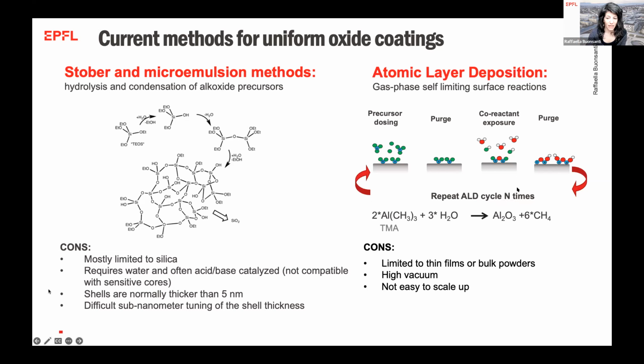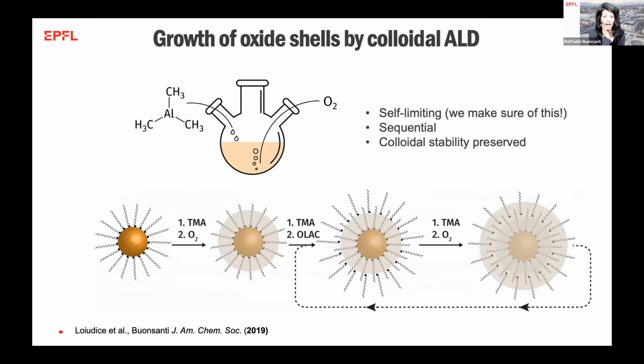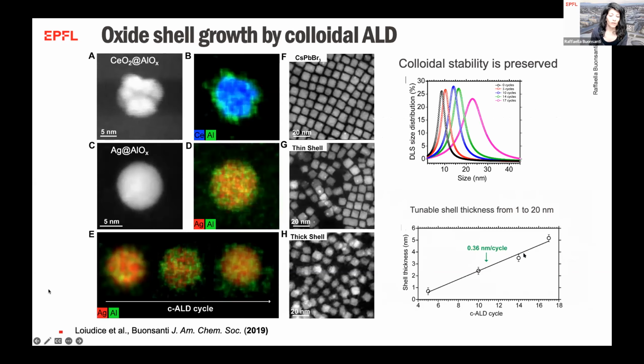On the other side, we have gas phase ALD, which is great to tune the thickness of oxide coatings. However, it's in gas phase, so it would be nice to keep our colloidal nanocrystals. So what we introduced is this colloidal ALD, which simulates the gas phase ALD, but occurs in solution and at room temperature. It is based on the sequential injection of a reactive precursor for the oxide and oxygen. Furthermore, we also add ligands during the growth. I like to highlight that these shells, in the end, are amorphous, hybrid oxide-organic compounds, and they possess, as I will show you, quite unique properties. Now, the first work on this colloidal ALD was simply to report that we could grow this shell around a large variety of cores.